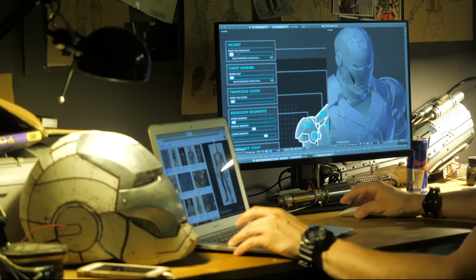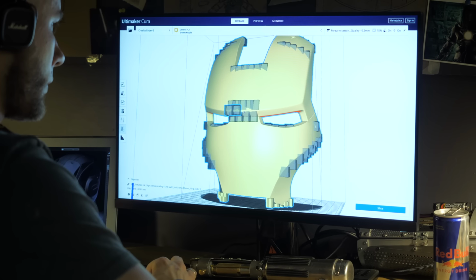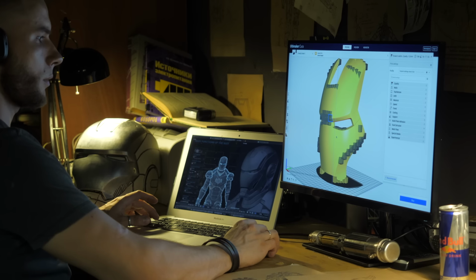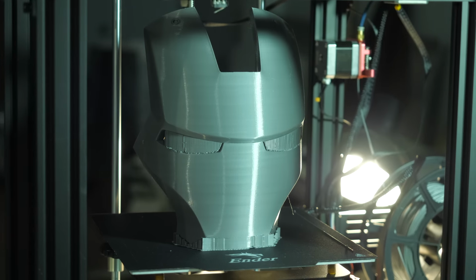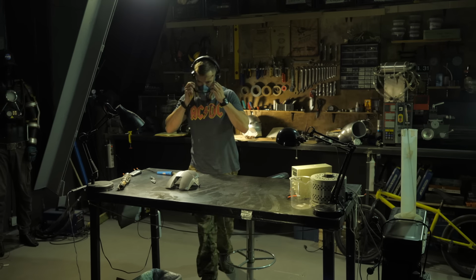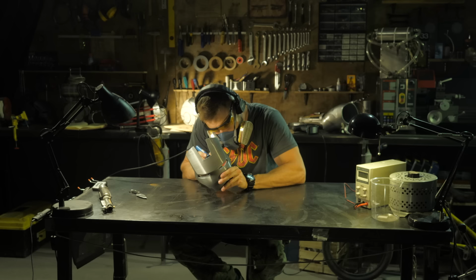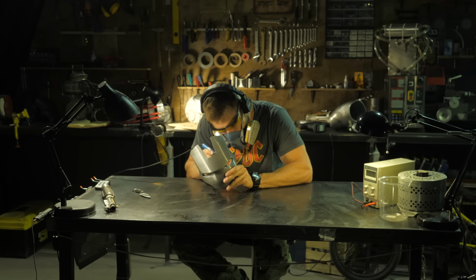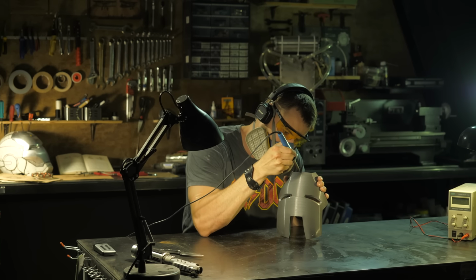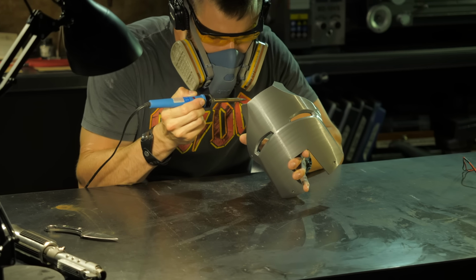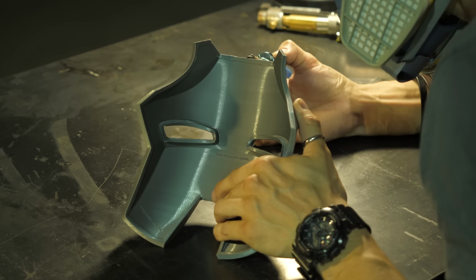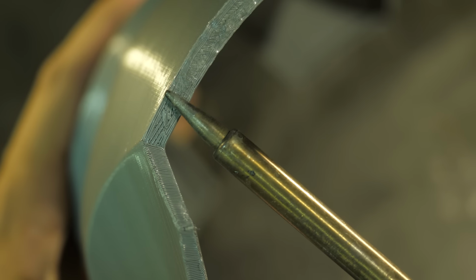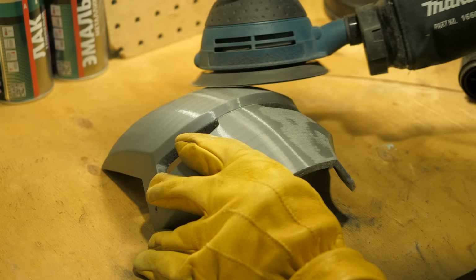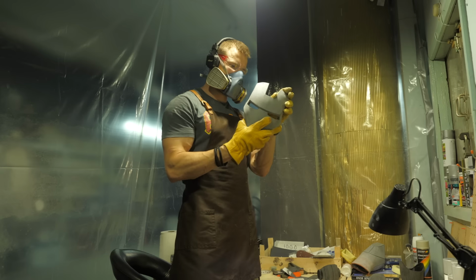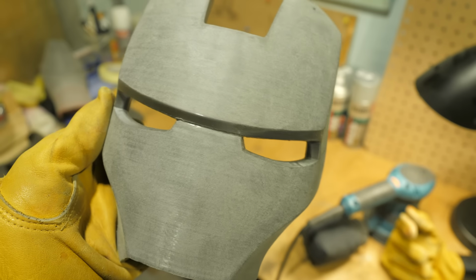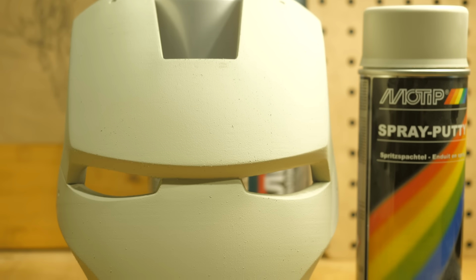The print settings are the same as in the previous steps, but we can play with the percentage of filling to get slightly stronger parts initially. Before immersing the mask in an electroplating bath and starting casting, prepare the part. After 3D printing, everything is the same as before: sealing, sanding, filling and priming. It is important that the part is sealed and doesn't allow water to pass through. The surface of the mask must participate in the electroplating reaction, so it must conduct electricity.